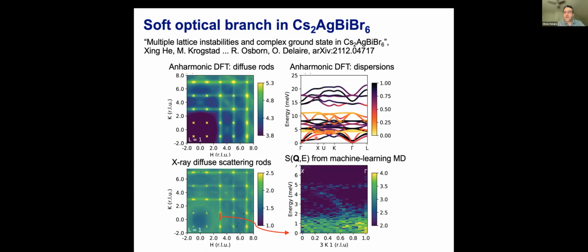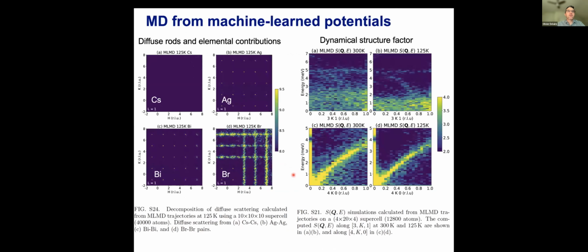through the zone center, we actually find that this is now associated with a low energy transverse optical branch, which is strongly overdamped, as we can compute now using full calculation of S(Q,E) using machine learned interatomic potentials and large scale MD. These types of simulations have really come a long way in just the past few years. It's moving quite fast. So we've been using this successfully in these systems, and we can now compute the full dynamical structure factor, including anharmonicity to all orders, you could say. And we see that there are some well-defined acoustic phonons in those systems, but you also have this strongly overdamped low energy transverse optic branch.